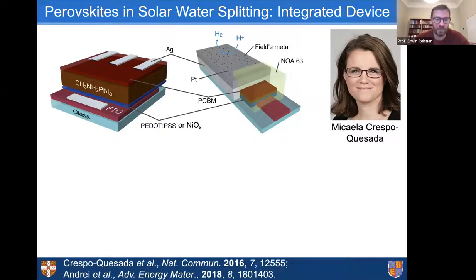And we also like to keep things simple. So what you need is conducting glass, of course, FTO coated glass you can buy. And then, again, this comes from the photovoltaics field, you take, in this case, just a methyl ammonium lead iodide perovskite, which was a very simple first one. And then you usually integrate this in charge separation layers. So you need to make sure you get directionality and pull your holes on one side and the electrons on the other side, to keep it very simple.